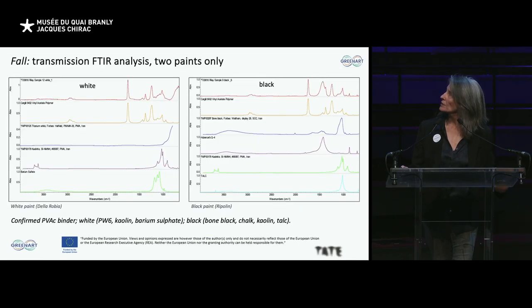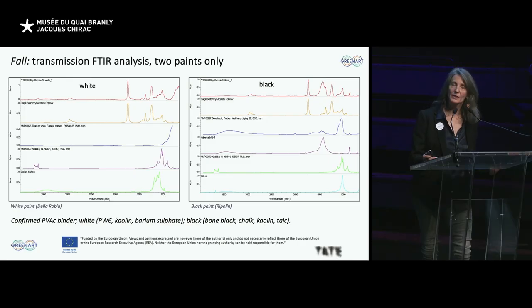You always have to have an infrared spectrum or two in a talk, so here are the examples this time. They're both polyvinyl acetate binder, fairly simple paints actually in lots of ways. The white was a brand that I haven't been able to find much out about, called Della Robbia. Titanium white, kaolin, barium sulfate, the usual culprits in modern paints, and the black is actually a Ripolin polyvinyl acetate paint, which we're investigating more in a slightly sideways project.